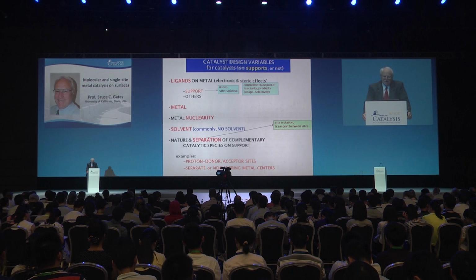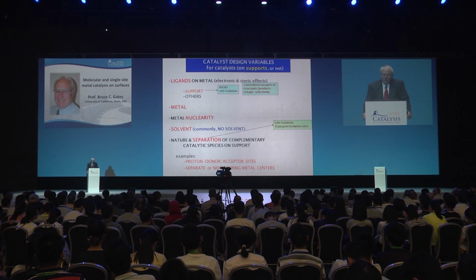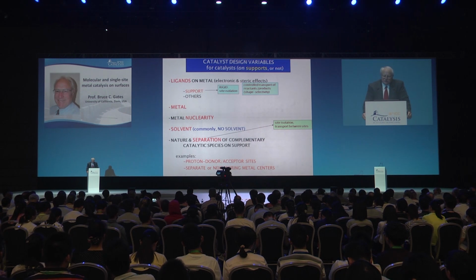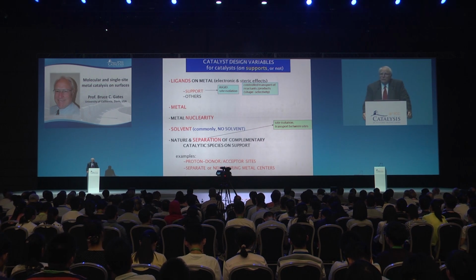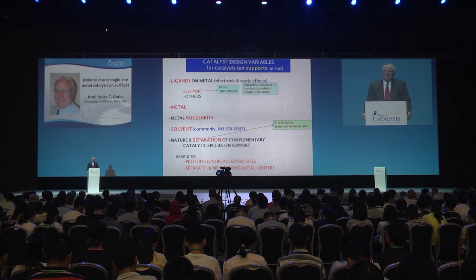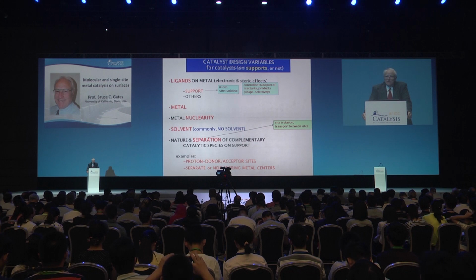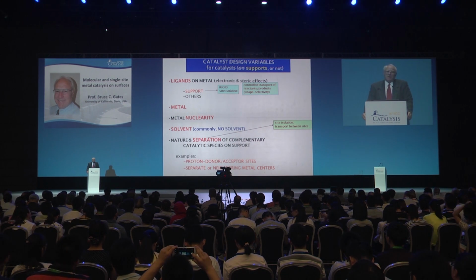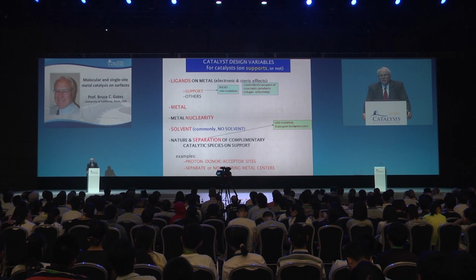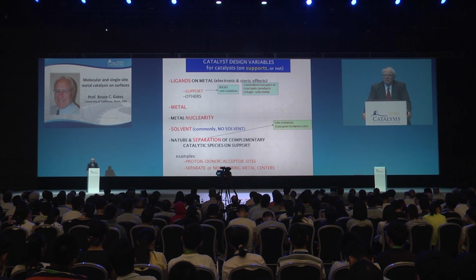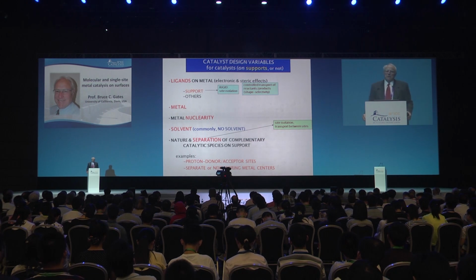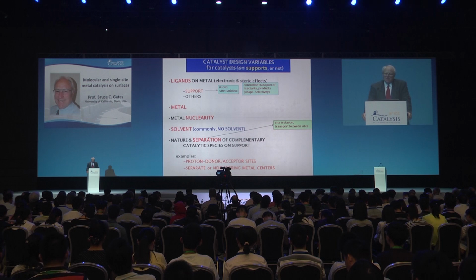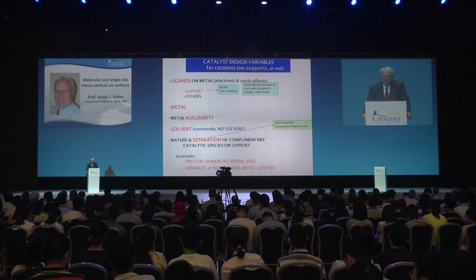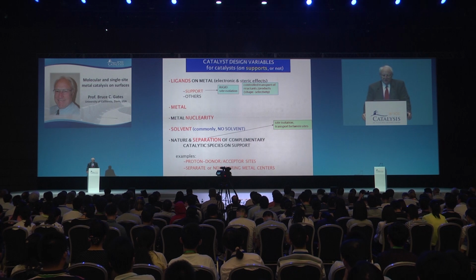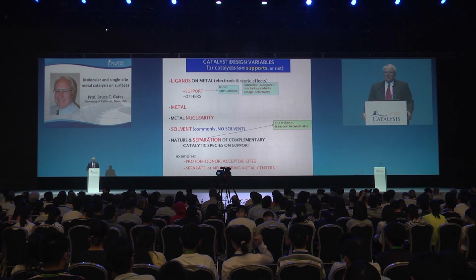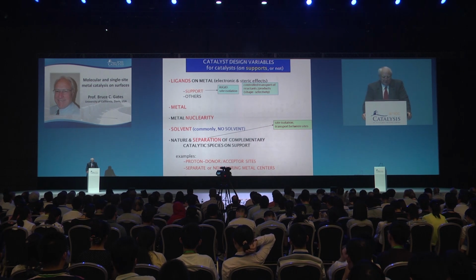So contrast the supported catalyst with those in solution. The catalysts on supports are isolated. They don't reach each other. They don't lead to formation of metal-metal bonds so readily as in solution because they are held apart from each other. And one has opportunities, taking advantage of transport phenomena, to control the influence of one site on a support on the action of another on the support by changing, for example, the distance between them because of transport effects. Obviously, another variable is the metal. Okay, and then the metal nuclearity.